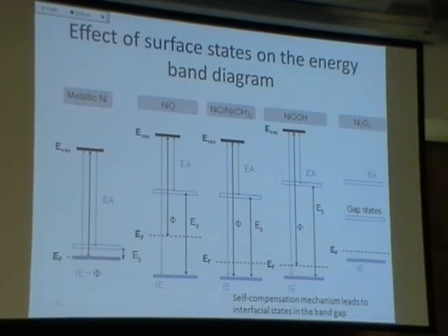They don't appear down here near the Fermi edge. They actually appear right in the middle. Right in the middle where you would put the LUMO of your acceptor. So what is this? These are recombination centers right at that interface. Alright, so a little doping can be good. A lot of doping, not so good, right? I mean, this is the classic OPV issue, no free lunch.